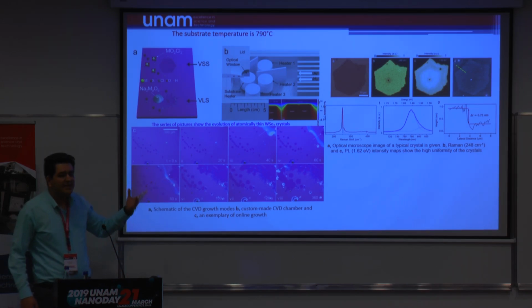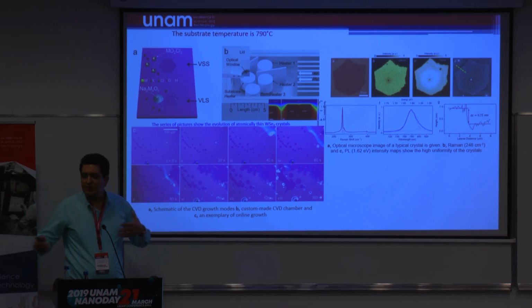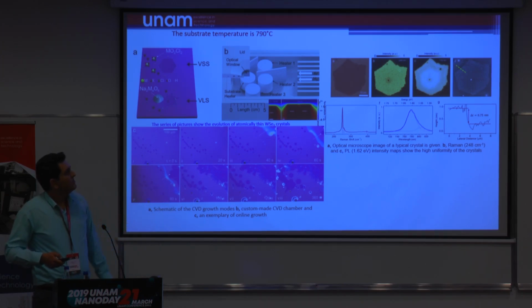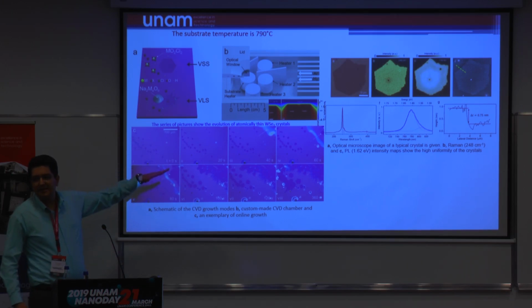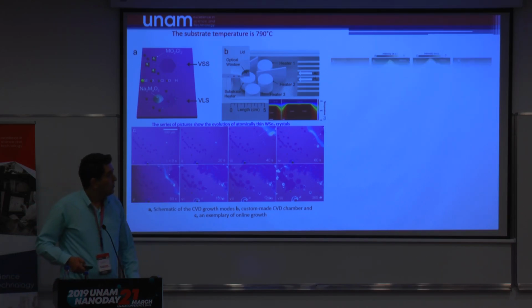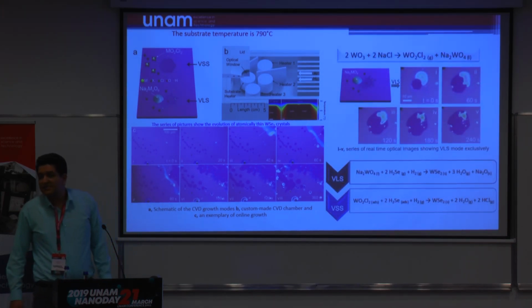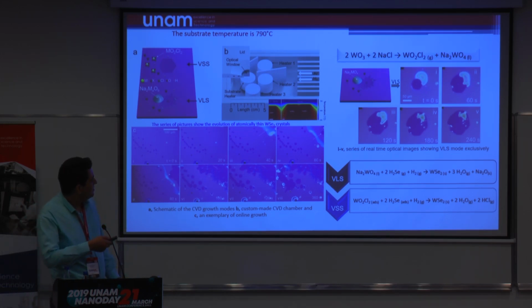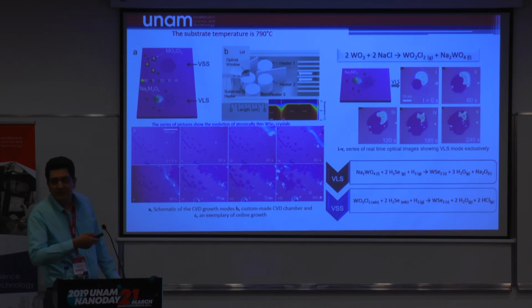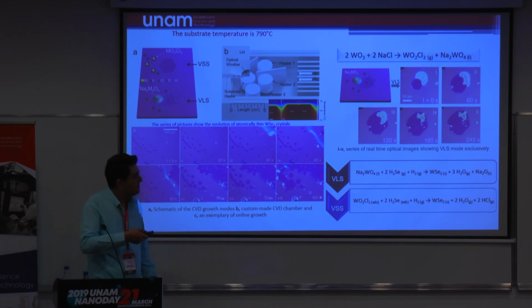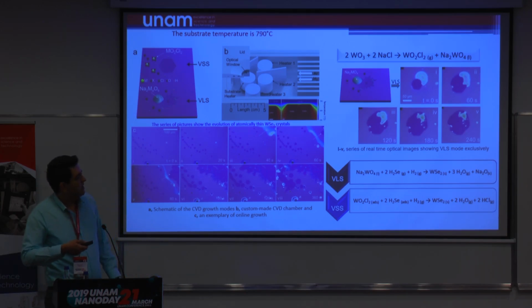We have the control. We can investigate the effect of each parameter, and we can also shut down the chamber at any desired time. So once you're satisfied with the growth, you can shut it down. This is also very favorable for studying the mechanisms of salt-assisted CVD growth. As we studied this growth, we found that there are two distinct growth modes, VLS, vapor-liquid-solid, and VSS, vapor-solid-solid, that induce growth. Also, with a series of control experiments, we found that hydrogen selenide is inducing the growth.